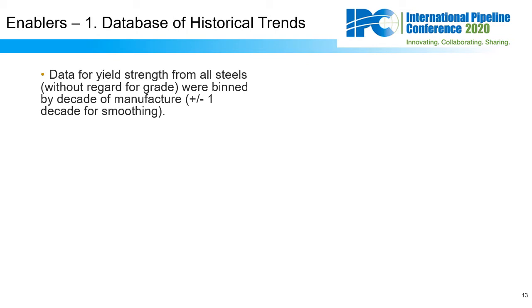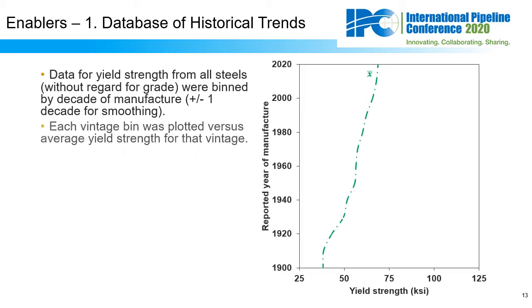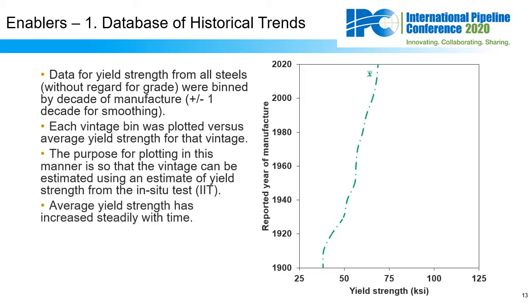Firstly, all the data in the database for our line pipe steels were binned by decade of manufacture, plus or minus 1 decade for smoothing purposes. Then these data were plotted against decade of manufacture. Here's an example of average yield strength versus vintage to get an idea of the appearance of the trend. In this case, our data show that strengths at the turn of the 20th century were low and gradually increased, which makes sense as there were technology-driven improvements in the strength of steel over time for line pipe.